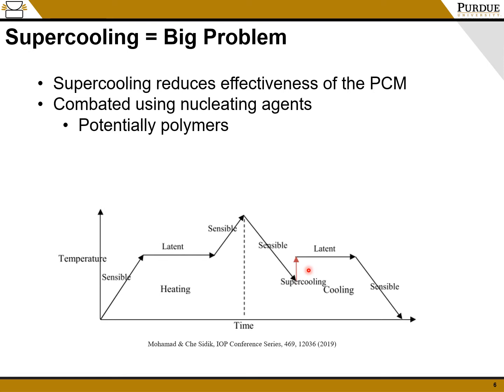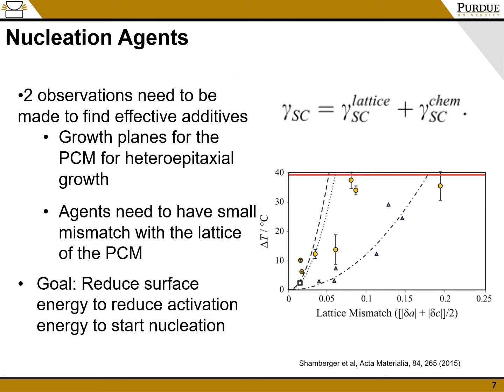The typical way to combat this is using nucleating agents. However, I also looked at the potential of using polymers. A nucleation agent is an additive that allows the material to start going through the nucleation process. And in order to find an effective nucleation agent, you have to know two things. First one is what growth planes of the PCM allow for growth in every direction. And then you need an agent that has a small lattice mismatch to that PCM's growth plane. And by doing this, you reduce the surface energy equation, you reduce this term. Reducing this term reduces the entire surface energy equation. By reducing the surface energy, you reduce the activation energy needed to start nucleation.